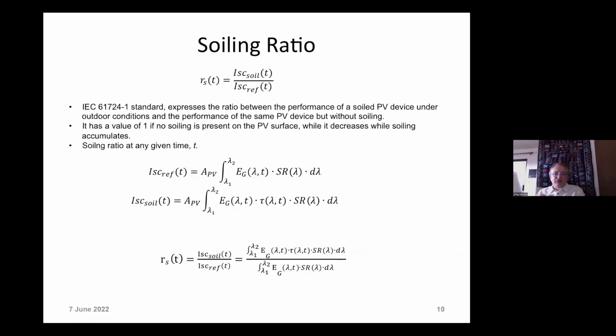All right, the soiling ratio is itself a ratio, of course, of the short circuit current at a given instant in time. And we take the ratio referenced to a clean panel. So there's an IEC standard, 61724-1, that expresses the ratio between the performance of a soiled device outdoors and the performance of the same device without soiling. In other words, it's clean. So if it has a ratio value of one, there's no soiling, while it decreases; we said we can have 0.5 even at a particular time.